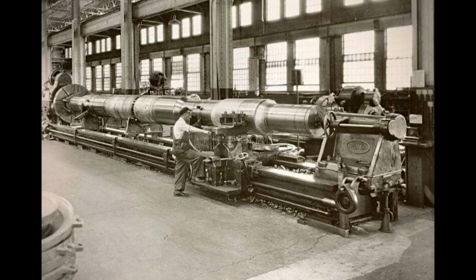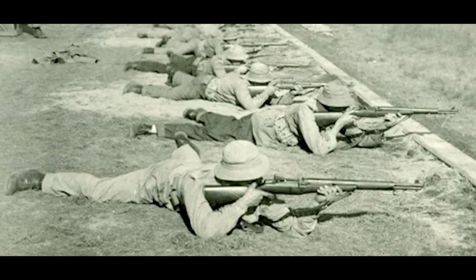This was where skeptics said mass production would fail. Heat treating wasn't new. Blacksmiths had been hardening steel for millennia. But the M1 receiver required precise carburization, adding carbon to the steel surface in exact amounts, followed by oil quenching, then tempering at 480 degrees for exactly 1 hour. The result had to be consistent across every receiver, creating a hardened shell with a tough, ductile core. Get it wrong, and receivers would crack under firing stresses or wear out prematurely. Get it right, and the M1 would survive tens of thousands of rounds and decades of service.